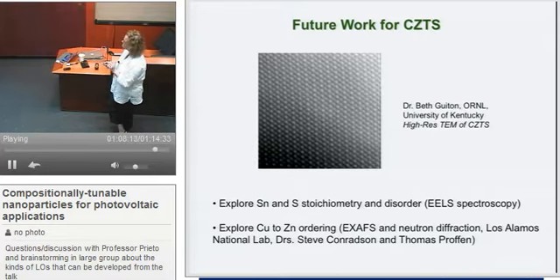And what's important about this is that she's able to take an electron energy loss spectra of a column of atoms and tell us if one of the atoms is not like the others. And from that, we figured out that we have tin atoms where we're not supposed to have them, and that's a trap site. We have copper and zinc pretty randomly oriented. And the other trick is that this electron beam, if you keep it on the particle too long, it evaporates the particle away. And that's another major problem in this field, is how your characterization methods interact with your sample. And it's taken Beth a long time to figure out how to just keep the sample stable and not changing over time.